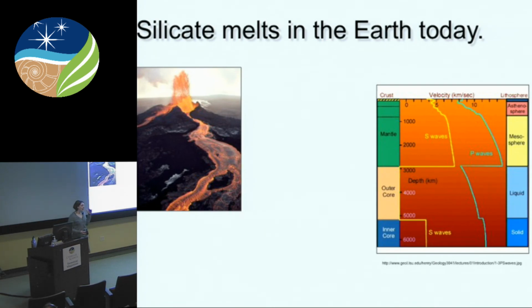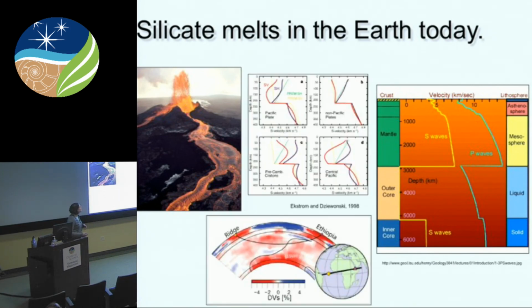We also know from established 1D global average seismic velocity models such as PREM or AK135F, which is my particular favorite, that there are regions in the Earth where the seismic velocities are slower. So that's what's shown here in this red, or in these curves here where we have velocity. So there are regions in the Earth where the velocities are slower than what we would expect for the average Earth. And the easiest way to explain this is by calling on the presence of silicate melts. But it turns out it's really, really hard to actually interpret the amount of melt present if we don't have a good equation of state for silicate melts at high pressure.